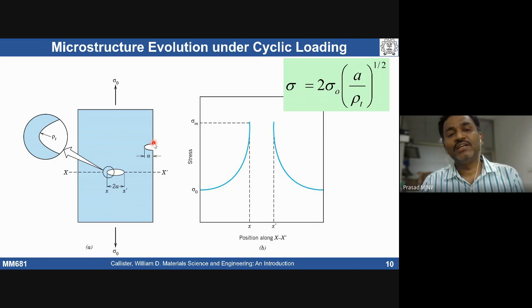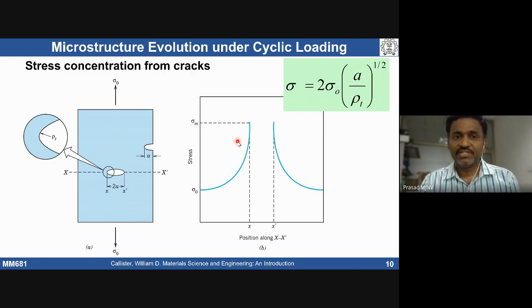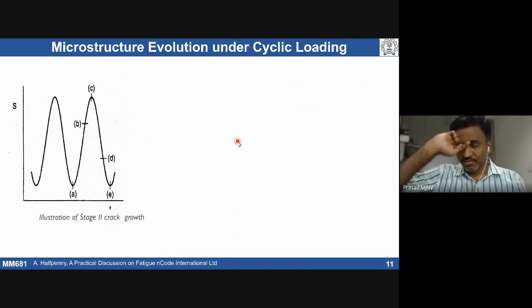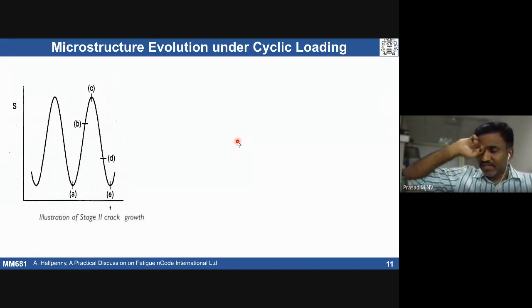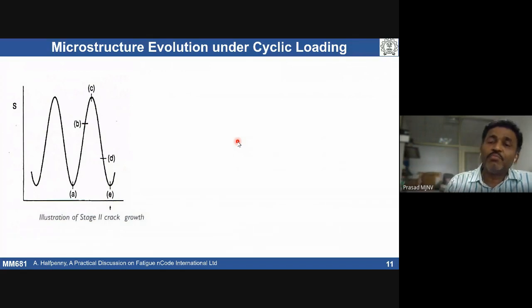So this is how cracks play a role, or any stress raiser that is present, where the stress is going to be higher, can lead to failure of the component under cyclic loading conditions. So this is basically stress concentration from cracks, what you have learned so far. Now the crack has been initiated. So how is this crack going to propagate under cyclic loading conditions? How does crack propagation take place?